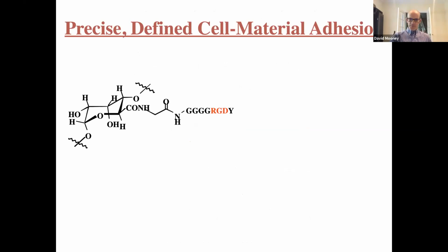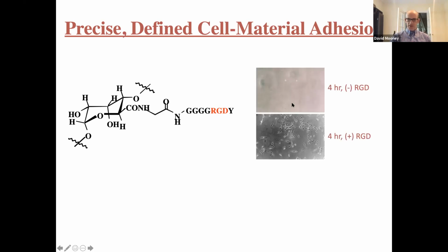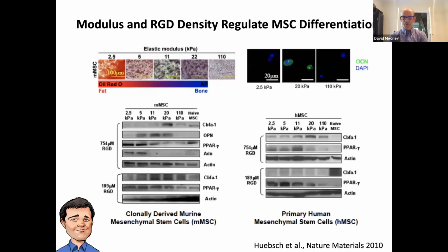So the last piece of this in terms of the system is we need a way for cells to actively engage with these materials. The cells from our body do not normally engage with alginate, which is derived from polysaccharides of certain bacteria. So in essence, that material acts as a blank slate. The cells in effect don't even see it. So we mediate specific interactions by conjugating small peptides to which cells have specific integrin receptors on their surface that mediate binding. And by doing this, we can take gels that otherwise would be completely uninteractive or unadhesive for cells and make them into materials upon which mammalian cells can readily attach, bind, and pull and push, which is the key feature for today.